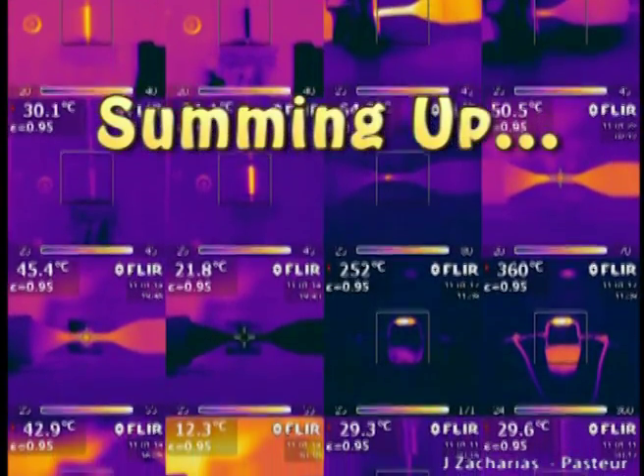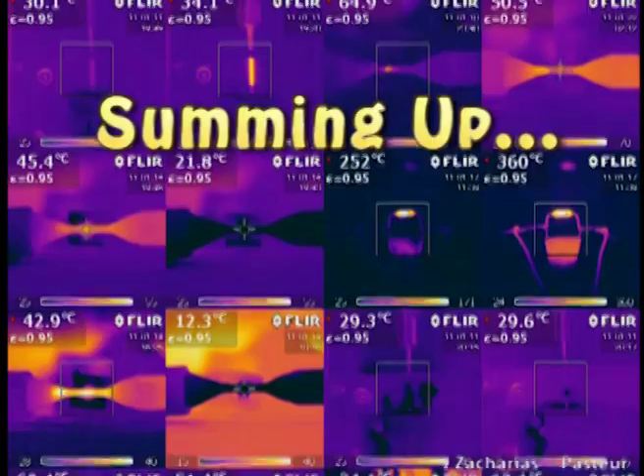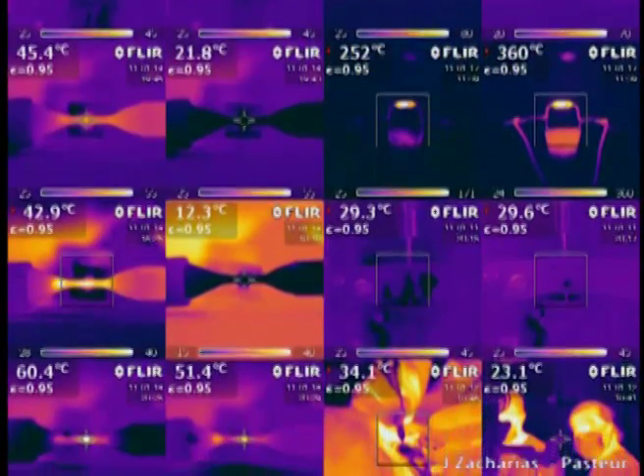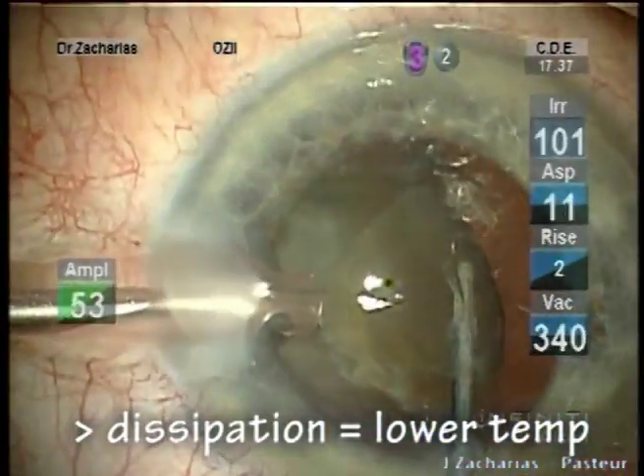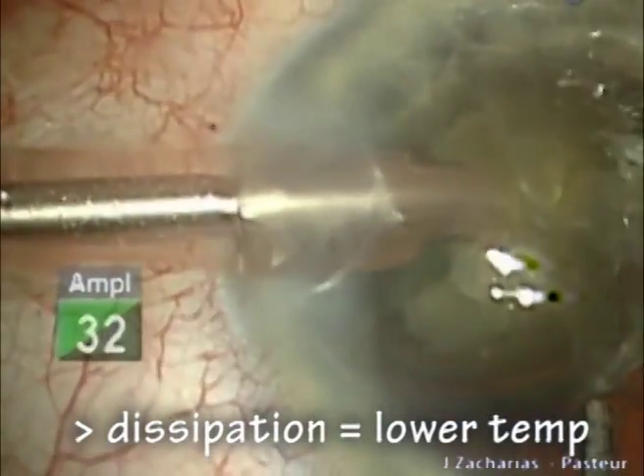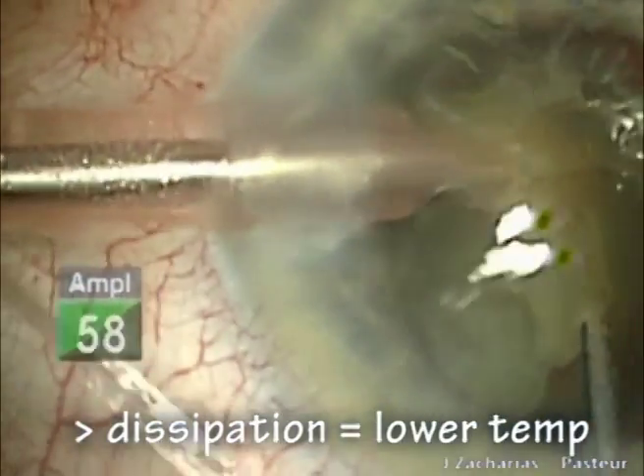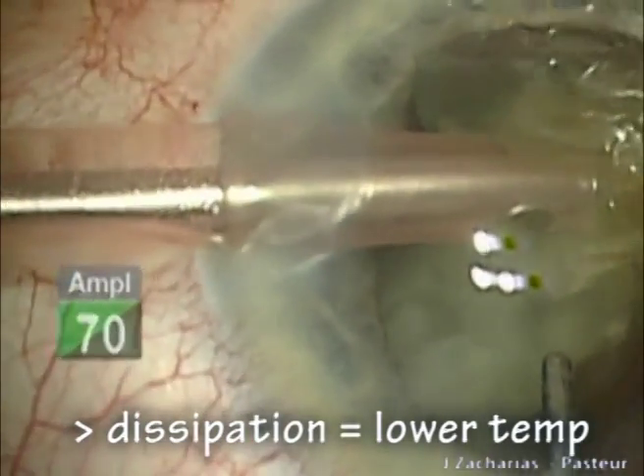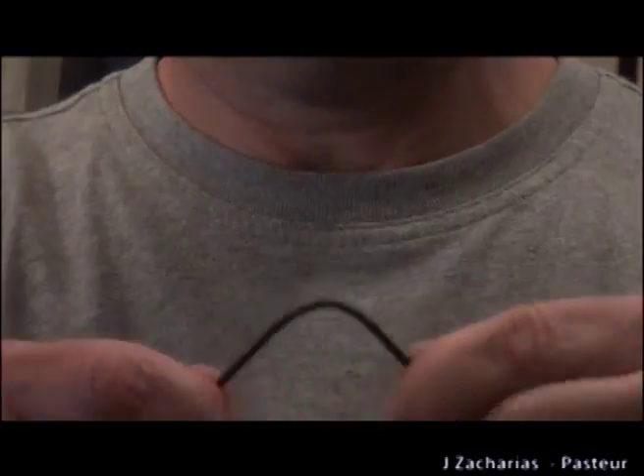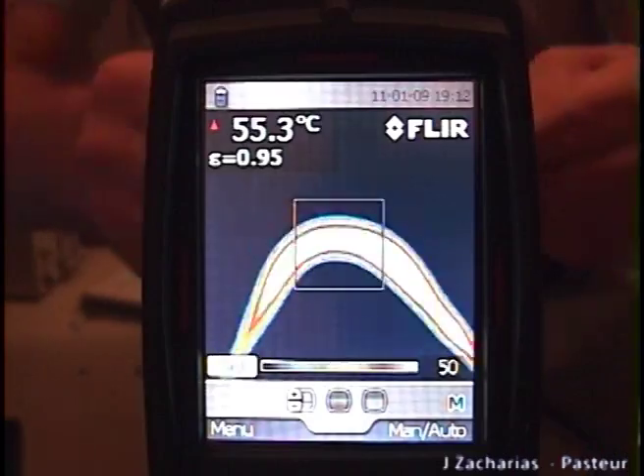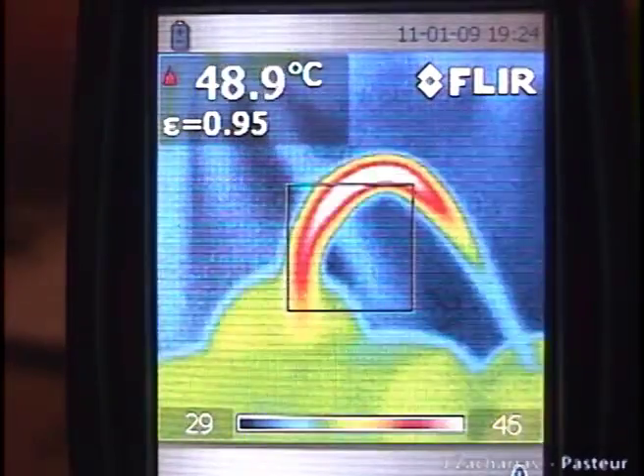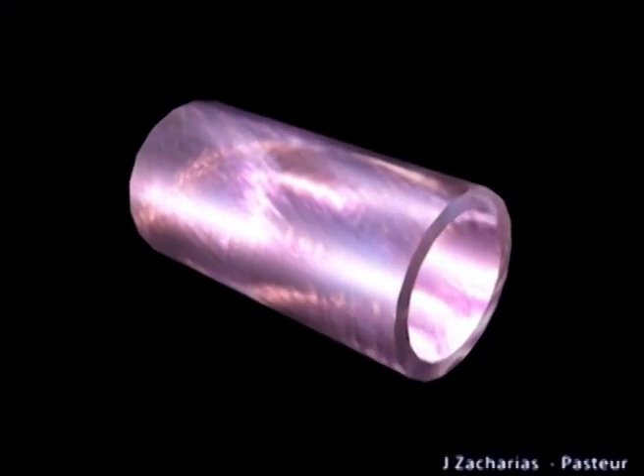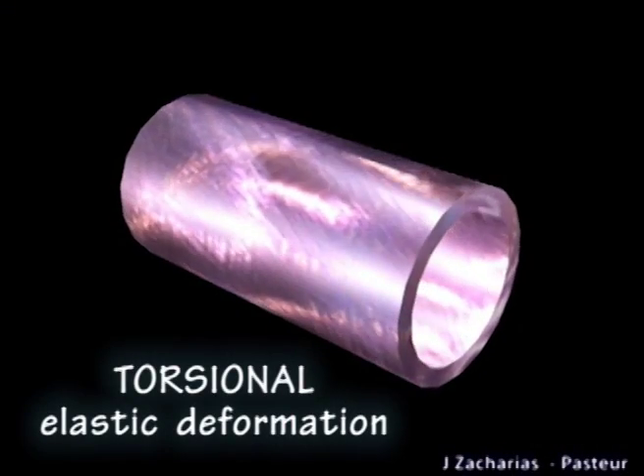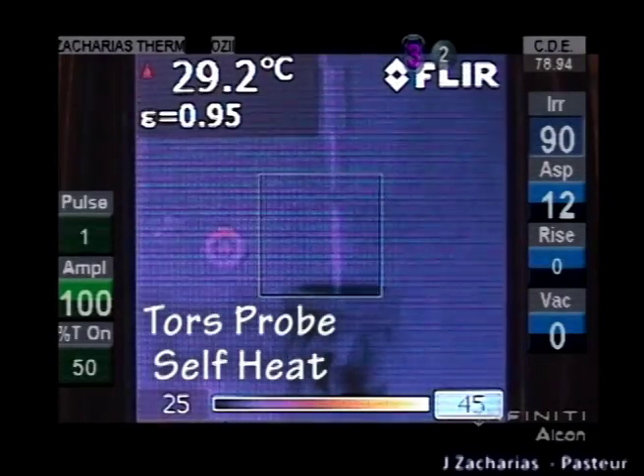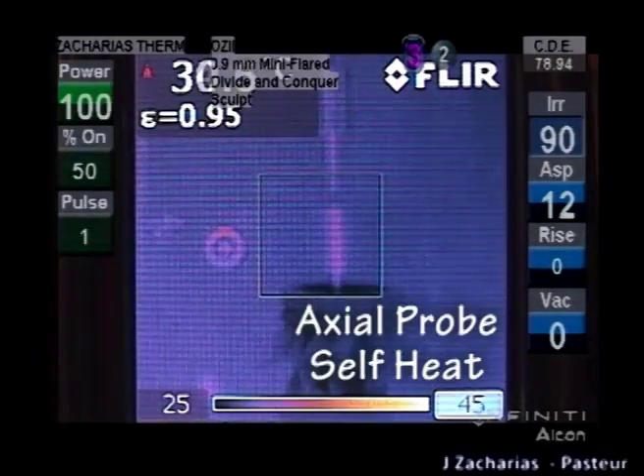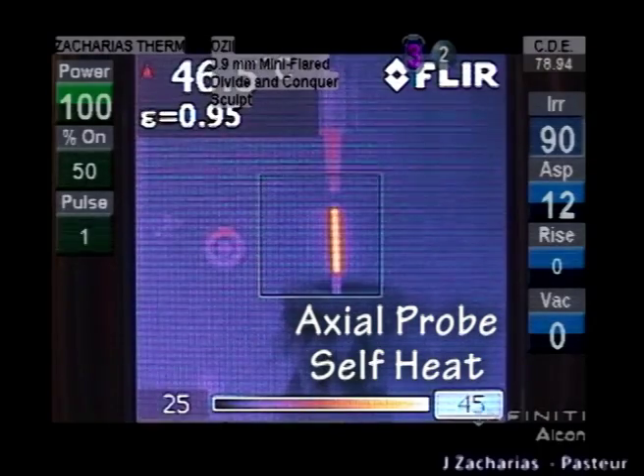These experiments were designed to sensibly detect differences in heat generation between torsional and axial Phaco terminals. In vivo, dissipation of heat by nerve tissues as well as fluid perfusion will effectively limit temperature to lower levels than those detected in these tests. A rigid wire bent repeatedly is subjected to plastic deformations, heating up by internal metal stress. The theory of internal metal stress as a dominant source of heat only with torsional is challenged by these bare probe tests showing that self-heating is more relevant with axial.